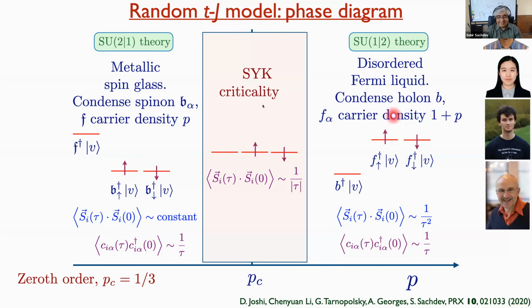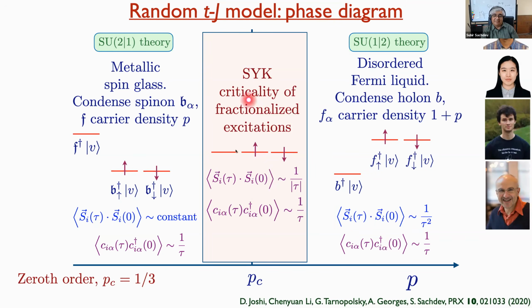And finally, the thing in between, well, here, of course, we can't solve it, but we can solve it from either starting with this theory or that theory, and we get very similar results. But we have to introduce another parameter, and from this theory of SYK of fractionalized excitation, we in fact get exactly what's seen in the numerics, the 1 over tau decay of spin correlations, at the same time, the 1 over tau decay of the Green's function. But notice,